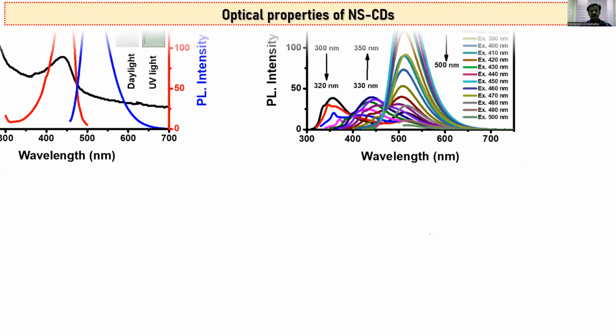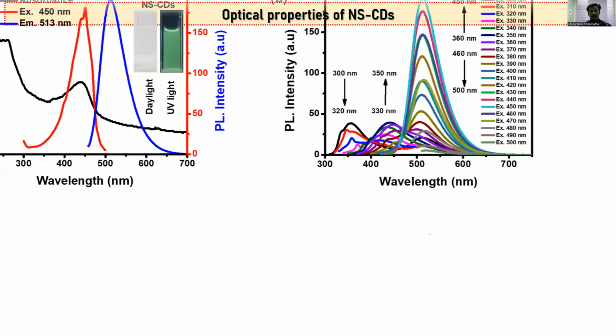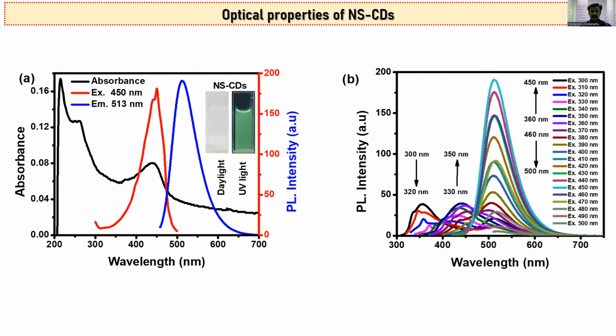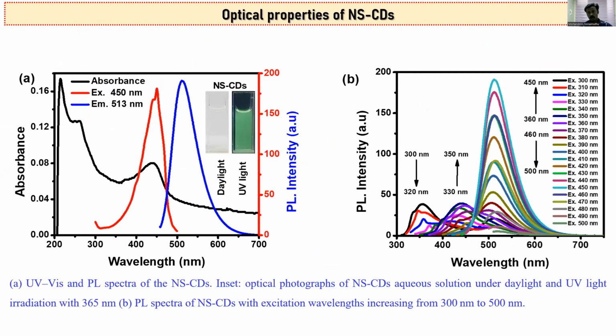The next one is the characterization method and the optical properties. First, we have to confirm the prepared carbon dots by UV-visible spectroscopy, and further confirmation from fluorescence spectroscopy. Figure A shows the typical absorption spectrum. The peak around 219 nanometer is assigned to the pi to pi star transition of C double bond C, and a shoulder peak appeared around 260 nanometer. It is also a pi to pi star transition, coming from C double bond N bonds in the sp2 carbon of carbon dots.